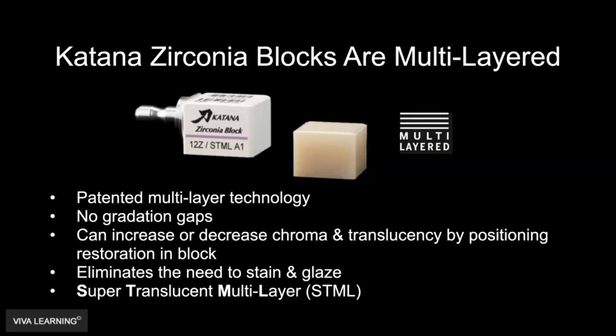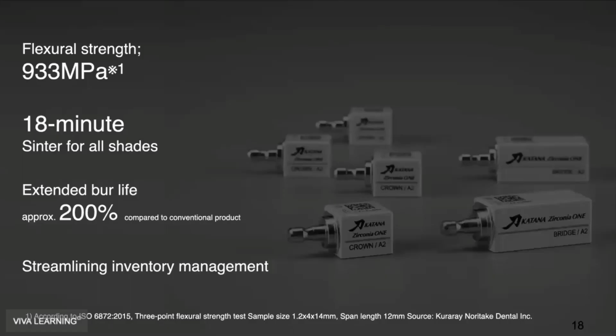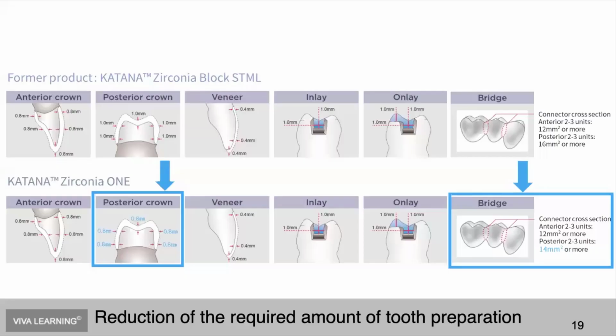They have now come out with their Zirconia 1 block. It still has this super translucent multi-layer with also increased flexural strength. So I think it went from about 750, if I remember, 800, to now the Zirconia 1, which is 933 megapascals. So super strong, but we can also reduce more. And we're also keeping it at that same 18-minute sinter for all shades. And it's increasing the burr life. And I don't have to keep as many burrs or blocks, I should say, in stock.